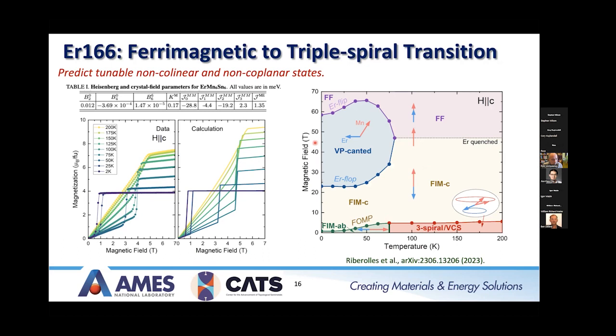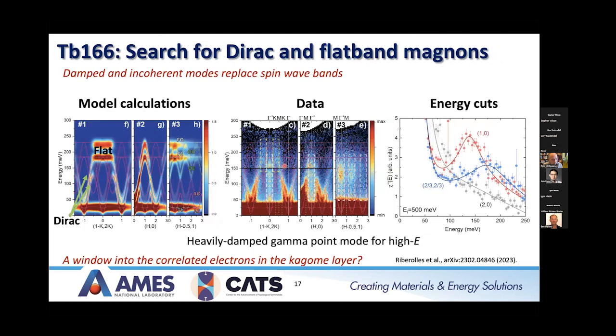Another interesting feature that's brought out is, up here before you get into the forced ferromagnetic phase at high temperature, you actually get into this region where the erbium moment is effectively quenched due to the Zeeman energy of the high field. Okay, so I wasn't sure how much time I had, so I thought I'd put this at the end. So I'll just go through this quickly, even though this is probably one of the harder ones to explain.